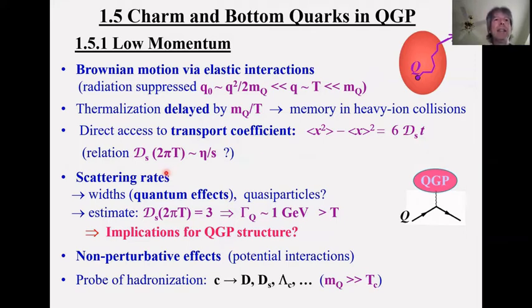Now, the key ingredient in this are the scattering rates of the heavy quark. And in a quantum language, these are nothing but the collisional widths of the particles. The question you can then ask is, if the widths become large, do we still have good quasi-particles in the medium? Now, I'm going to make a little estimate here based on what we'll see later. Let's say that this dimensionless scaled heavy quark diffusion coefficient is about 3. And then a little calculation reveals that the collisional width of the heavy quark is actually about 1 GeV, and that is larger than the typical temperatures we encounter. While it is still smaller than the charm quark mass, definitely smaller than the bottom quark mass.